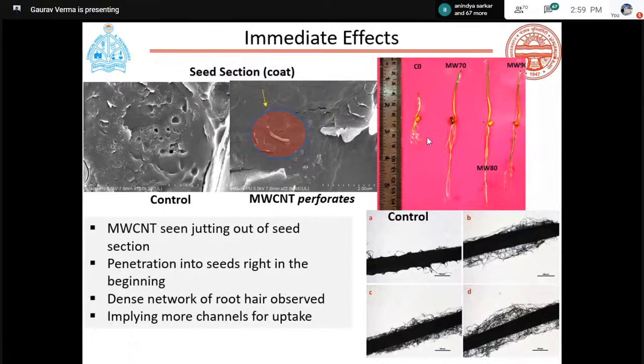Now, if you look at the control of these seedlings, all these are actually lab experiments, and they have been undertaken in a petri dish. You will understand that the control behaved in a very inhibited manner as compared to the primed seedlings, which started to grow really fast in both directions. What you see above the seedling is the shoot, while the root is below it, and this was much faster if you keep just a scale around to compare. The amount of growth was really phenomenal, and we needed to understand why would this happen when you're allowing a foreign material to enter a bioorganism or a plant.